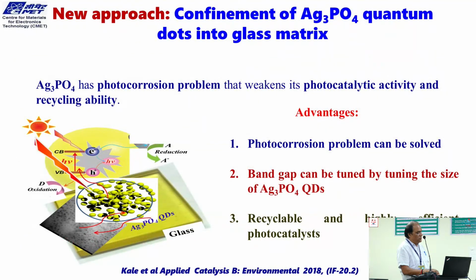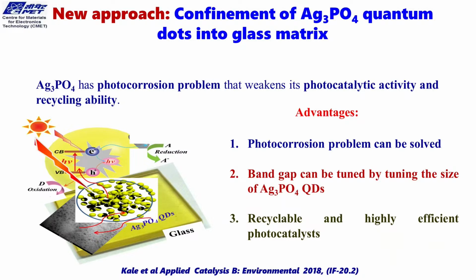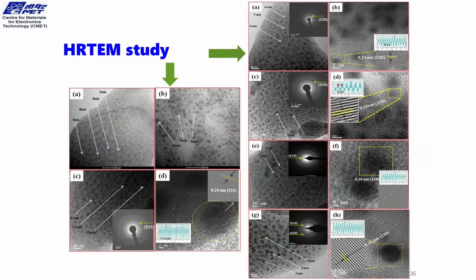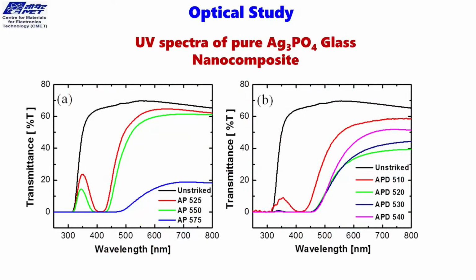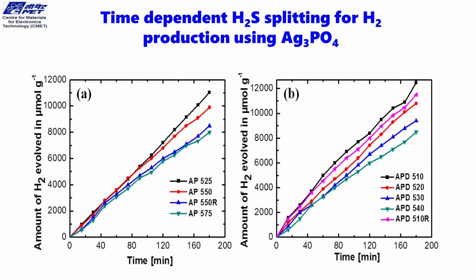Then we also developed silver phosphate, a very well-known compound which can be used as a catalyst for hydrogen evolution. But this silver phosphate is very unstable. So we stabilized it in glass, and we also prepared different particle sizes in the glass. You can see all the nanoparticles embedded in the glass, and this glass can show different optical properties. And you see here a very huge amount of hydrogen evolution is possible with very low particle size.